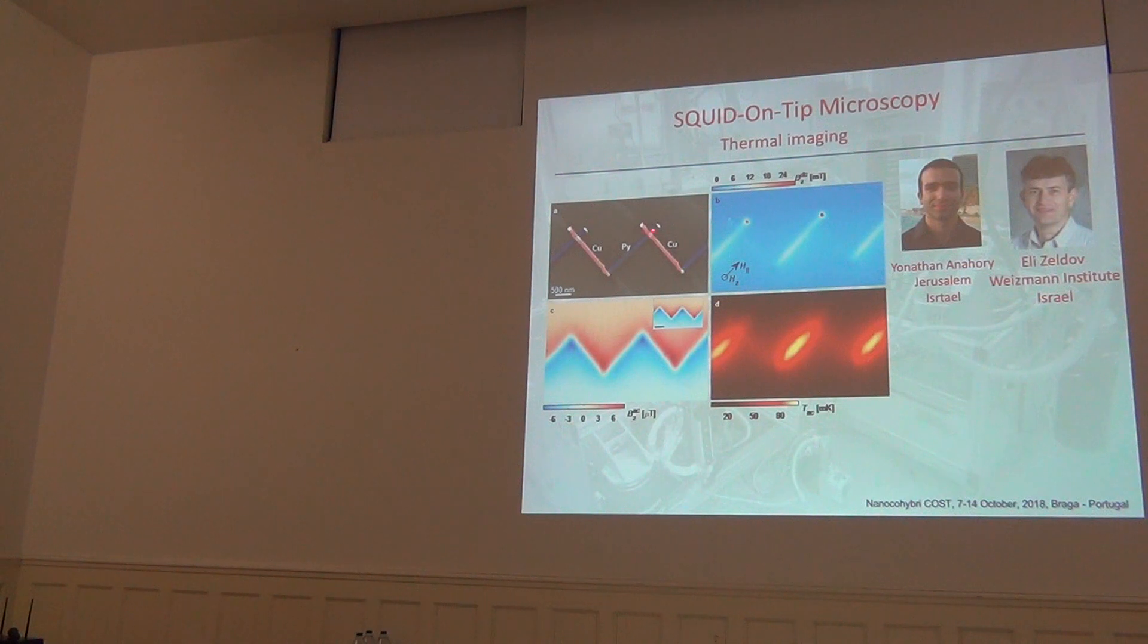And with this thermometer, for instance, here, a test experiment, you have some lithographed wires of permalloy in blue here and copper in red. And what you see here, for instance, this is a SQUID experiment. You see that permalloy, which is a ferromagnetic material and magnetization vector is aligned in the axis, you only see very strong spots in positions where the magnetic field gets out of the sample. And you don't see copper wires. Now, if you put a current, electric current, this electric current by Biot-Savart will create a magnetic field and you can detect it immediately because the current flowing like this, you will have a part of magnetic field getting out of the screen and another part getting in, and this is coded as blue and red color so you get immediately the magnetic picture of the story.